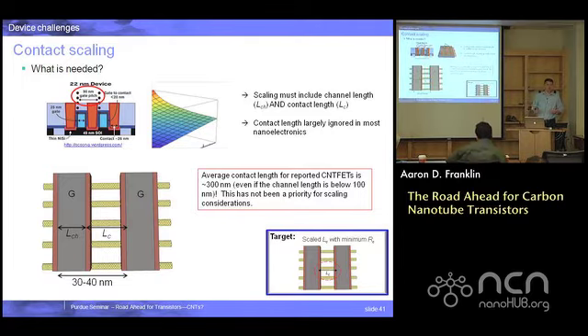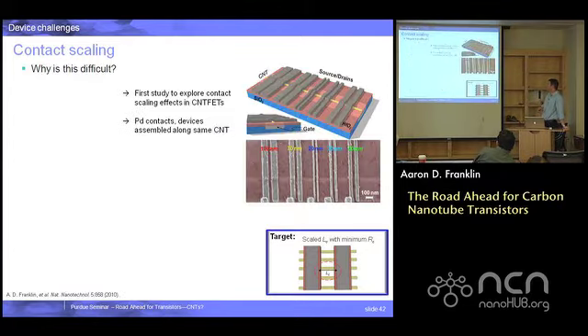And I think the motivation was that the biggest problem with silicon was short channel effects from making the channel small. So what should we fix? Well, it's making better devices with short channels. But all along the way, in the back of the minds of the technology people, we have to make small contacts too. And there were some people who actually felt that, based upon some proper motivation, small contacts may even be better for nanotubes because you enhance the field there, they're Schottky barrier controlled, so maybe injection improves. And so we looked at it experimentally to get a feel for how good or bad the situation is, built a set of devices along the same nanotubes, and scaled the contact length. So the channel length remains about the same.